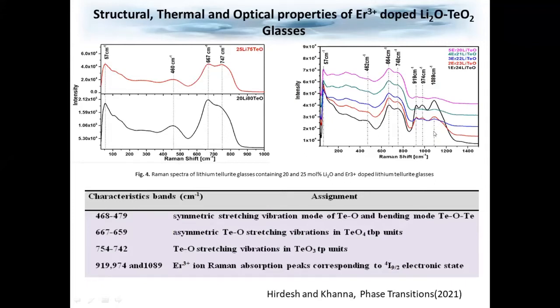And here we see a very interesting effect. These high frequency bands from 900 to about 1200 centimeter inverse completely suppress when you increase the erbium oxide concentration. So these are the concentration quenching effects which we see in the erbium doped samples, but we don't see them in europium doped samples.